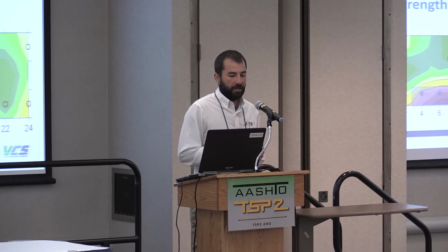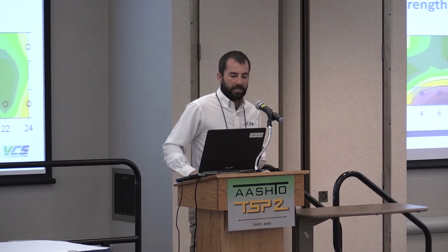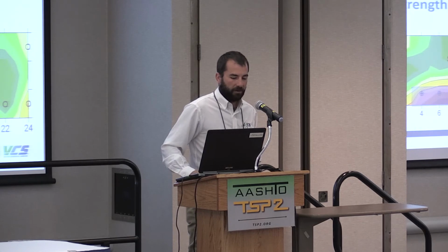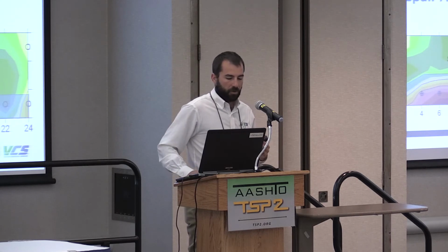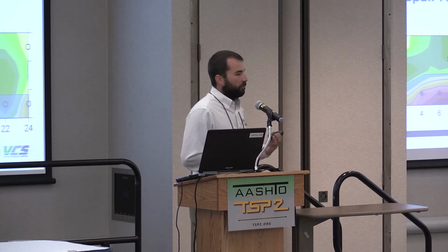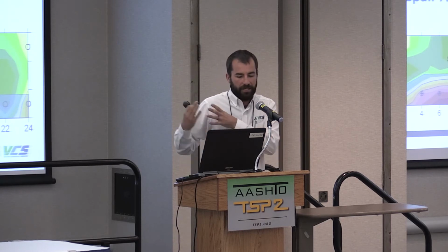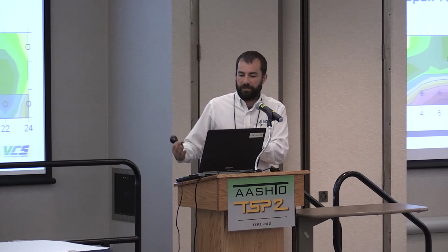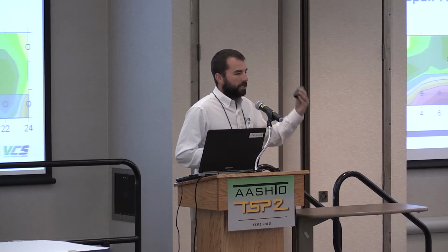So if we look at the in situ compressive strength of the concrete as well, you can see that there's some weakened concrete a little further out beyond this and here. This is where that delamination's really growing too. And so our total repair quantities are now going to be this area. If we just had relied on sounding, we would have underestimated the repair quantities easily by half, or even more. And so using a technology like acoustic impact echo surface wave velocity, we can better refine that quantity and understand what's going to need to be repaired.